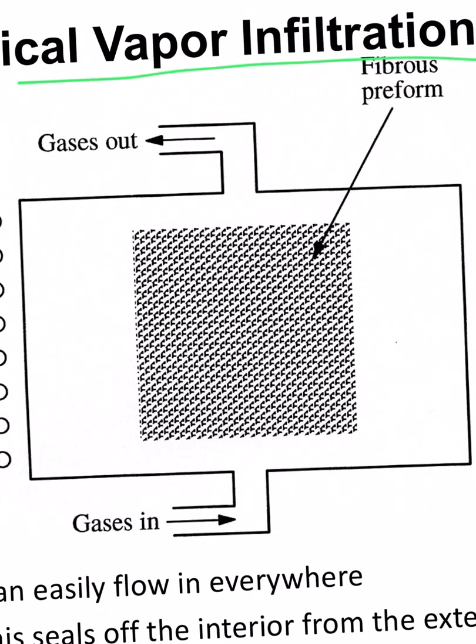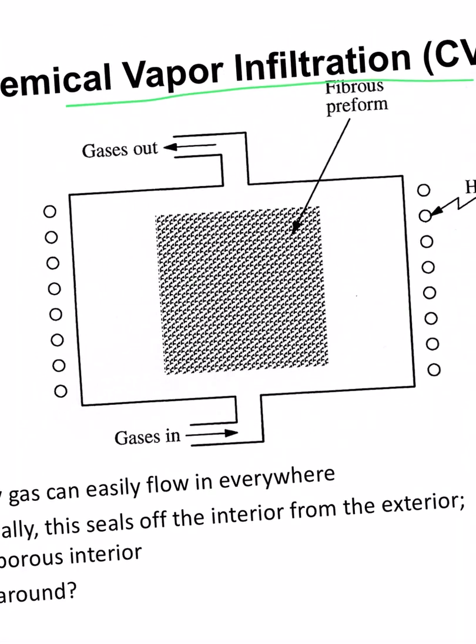So if this is our reticulated carbon skeleton, and we are bringing in a gas that has our tantalum precursor in it. Precursor. So some kind of gas that has molecules that contain tantalum, and that gas hits this hot surface, all right, and as soon as it hits the hot surface, it makes tantalum. All right, that's the nature of this precursor. And everywhere else it hits the hot surface, it makes tantalum. All right, but the issue here is that you don't just want to treat the surface, you want to treat the interior, and what happens is you just keep depositing tantalum on the outside because that tantalum decomposes at the first hot surface it sees, not every surface that you're interested in. You want the entire skeleton coated.